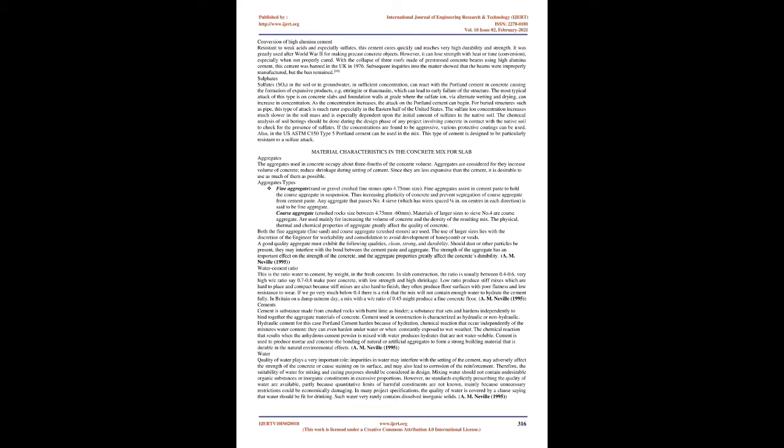Mechanical failure. Cracking of the concrete section is nearly impossible to prevent; however, the size and location of cracks can be limited and controlled by appropriate reinforcement, control joints, curing methodology, and concrete mix design. Cracking can allow moisture to penetrate and corrode the reinforcement. This is a serviceability failure in limit state design. Cracking is normally the result of an inadequate quantity of rebar, or rebar spaced at too great a distance.